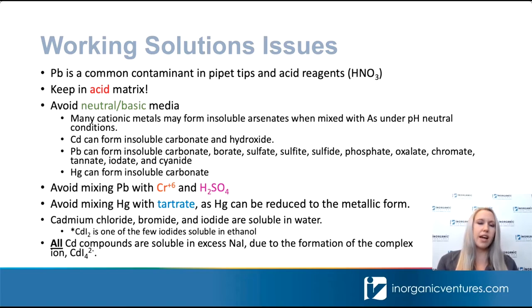Arsenic is not really going to have issues by itself under these conditions, but what happens is that under pH neutral conditions, arsenic will form insoluble arsenates with several cationic metals. So you do want to avoid mixing arsenic with other metals in basic or neutral conditions. Some other issues that will occur in basic conditions are that cadmium can form insoluble carbonates and hydroxides. Lead can form several different types of insoluble forms, and mercury can form the insoluble carbonate.